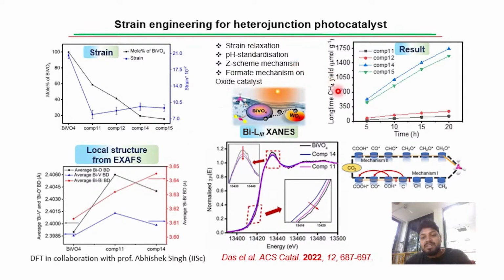And when we performed the CO2 reduction study, we found a very high yield with nearly 100% methane selectivity. With the composite 14, after 20 hours the activity is still there. Then we explained the electron transfer mechanism from the tungsten oxide side to the bismuth vanadate side, from bismuth L3 XANES spectra, and from DFT and DRIFTS in situ IR studies, we estimated the reaction is going through the formate pathway, not through the carbide mechanism.